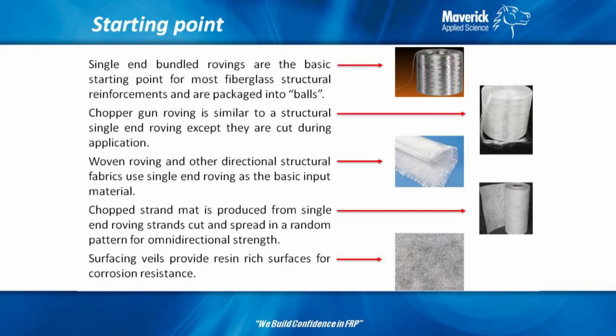Beyond that, chop strand mat is one of the basic building blocks of fiberglass parts. It's used in corrosion barriers and structural laminates. There are parts built strictly from chop strand mat, and that's all you would need. Chop strand mat is basically these single end rovings chopped into a random pattern and sprayed onto a flat area. And that rolled good is then applied as a structural reinforcement when it's saturated with resin.